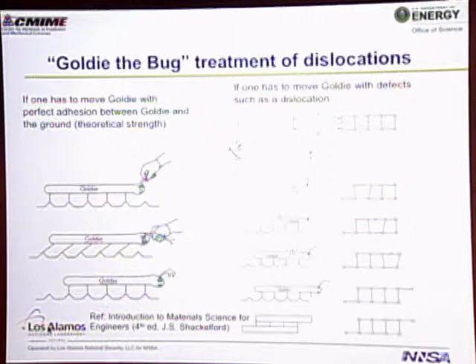However, if you move Goldie with a defect such as a dislocation, you give Goldie a swift boot in the behind right here, you break one bond, she gets kind of this kink in her, and then this bond can be gradually moved along. And so you can see that here. Goldie's much happier at the end. We end up seeing that we have our step here. And this is the way that real materials actually deform.